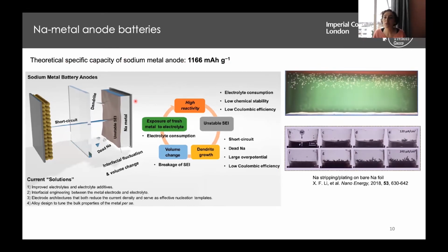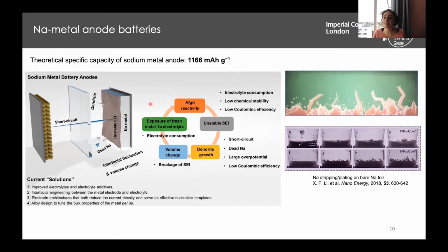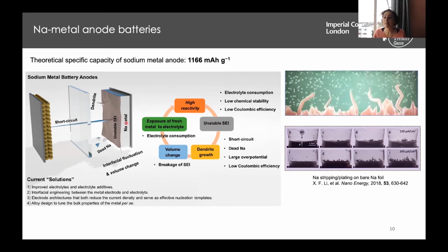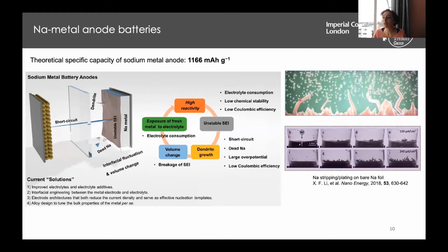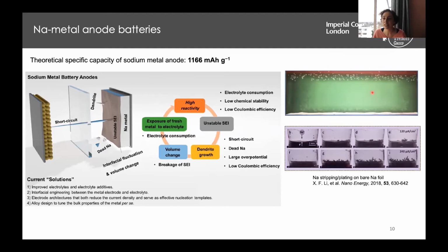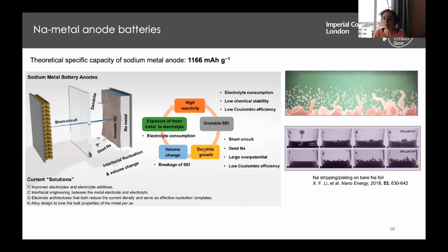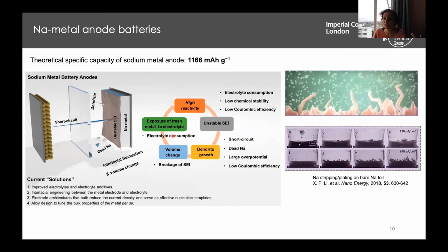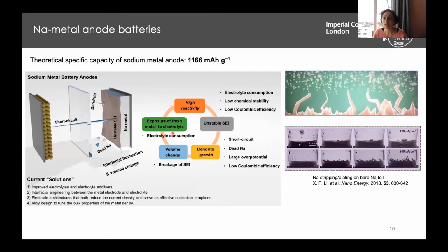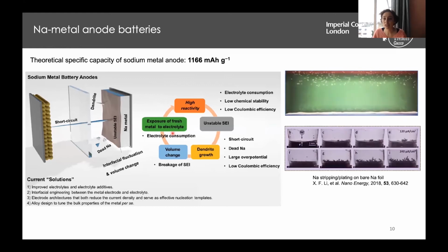But the problem is that when we want to use sodium metal as an anode, because of the high reactivity of the metal, when we use it with liquid electrolytes, a very unstable solid electrolyte interface forms on top of the sodium. And because during cycling, charge and discharge, dendrites grow, and therefore there's a volume change and exposure of fresh metal to the electrolyte, and that means that we lose a lot of sodium that becomes dead after continuous cycling.